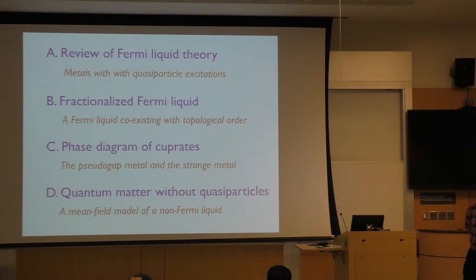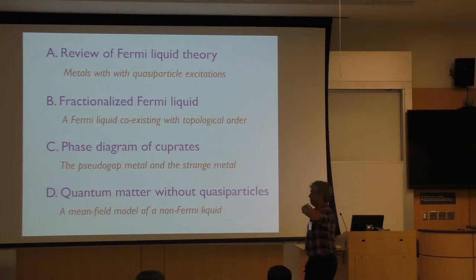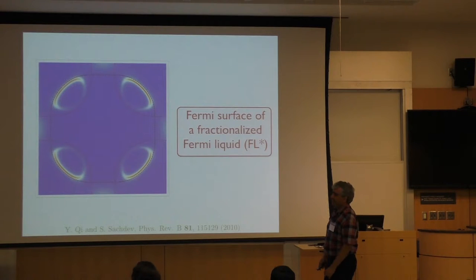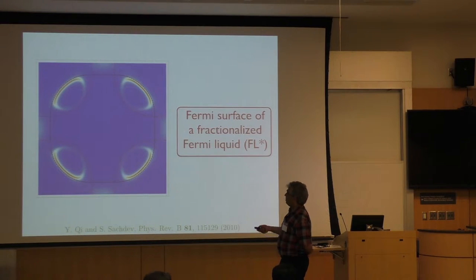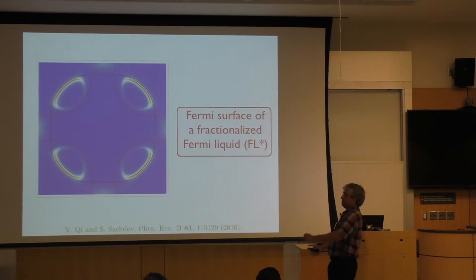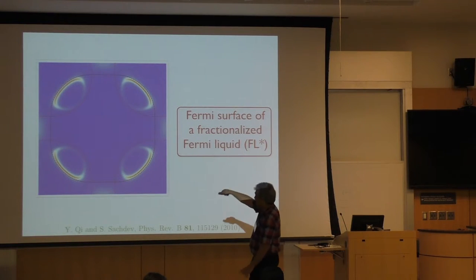Question: Would there be some other proof of this FL* other than seeing the pocket in some possibly distant future experiment? Answer: Well, we've been talking about it. Is there a direct manifestation? That's what Seamus keeps asking us. I think somehow you want to see this backside. It's very hard to see in photoemission because that involves removing an electron. If you can do an experiment where you don't remove an electron from the sample, then really the intensity of the front and backside are the same. You could imagine putting in a zinc impurity and looking for Friedel oscillations, or putting in a magnetic field and seeing quasiparticles go around.